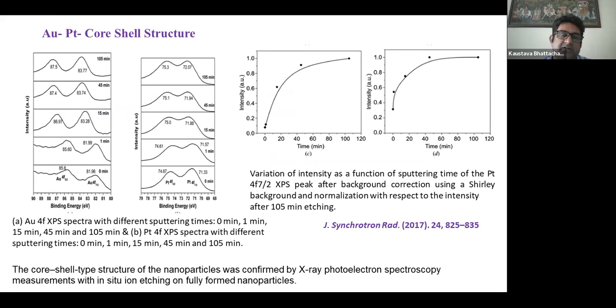Say we have a core shell material where the Z is very nearby, for example gold and platinum. Both SEM and TEM usually give us near. The problem is that if the Z value is very nearby, identifying exactly the core shell with SEM or TEM becomes a tougher thing. Here XPS can play a stronger role.